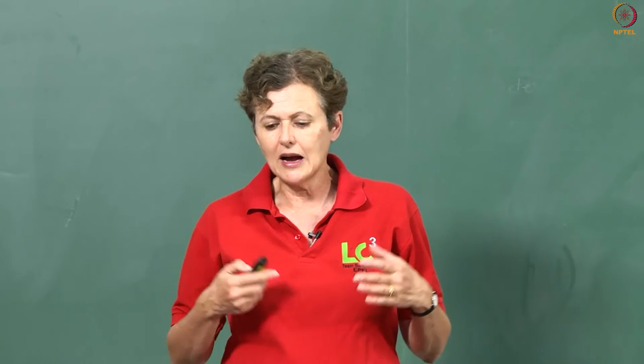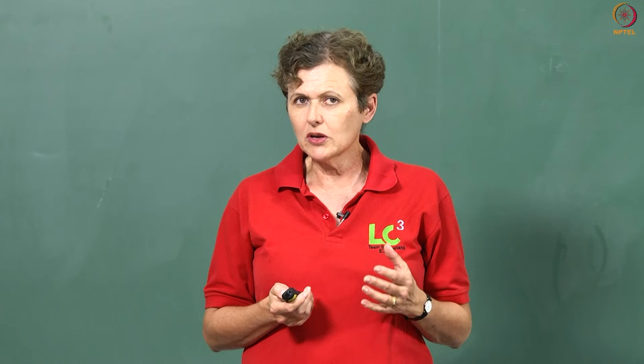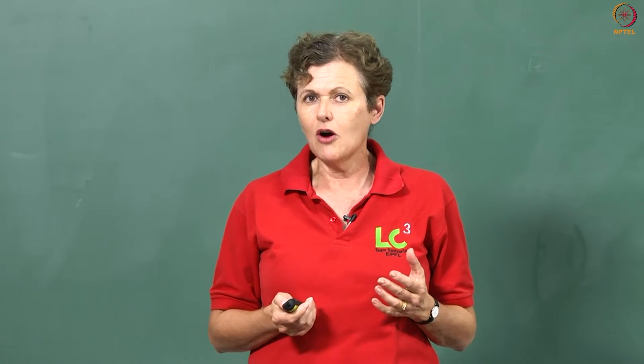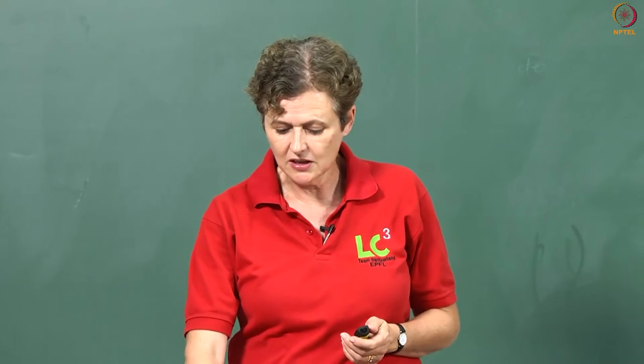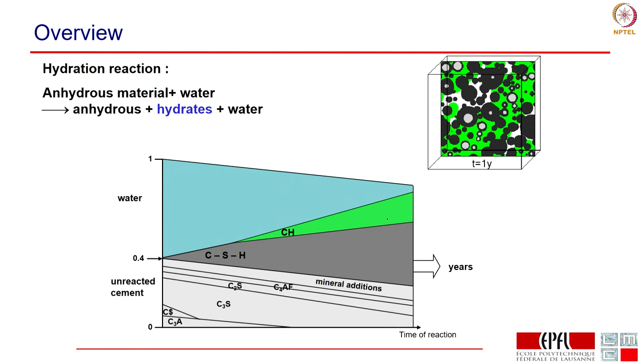What are we trying to do? The idea is that what is happening in cement and concrete is you have this hydration reaction. During this hydration reaction the water reacts with the cement to give you hydrates. In the simple case of just C3S or alite, this would be the anhydrous phase reacting and the hydrates forming calcium hydroxide and CSH. In the more complicated case where we have cement, we have all the different phases in cement and then we have some other hydrate phases.